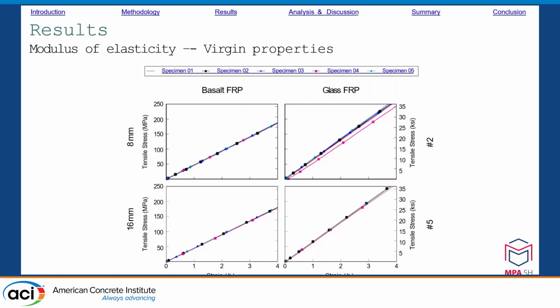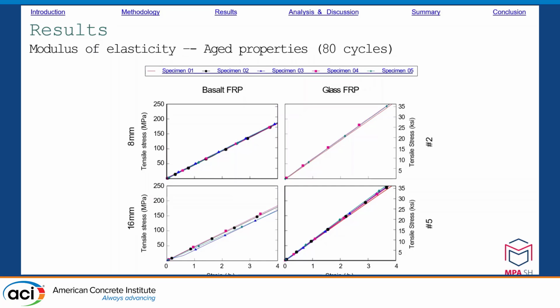fiber rods. The graphs of the samples after 80 freeze-thaw cycles show only slight changes in their slope compared to the previous samples after 0 freeze-thaw cycles. The calculated modulus of elasticity hardly changed.